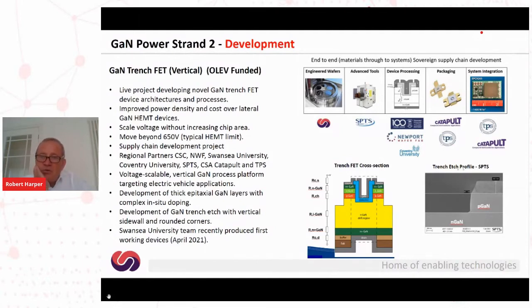Mike's mentioned that we're working with SPTS on GaN trench, but if you look at the bottom right of the slide, you can see some of the work that's been done at SPTS in developing the vertical trench etch for this type of device. We've etched down through the magnesium doped GaN onto the N-GaN, and we will have a vertical channel along the vertical edge that you can see there.